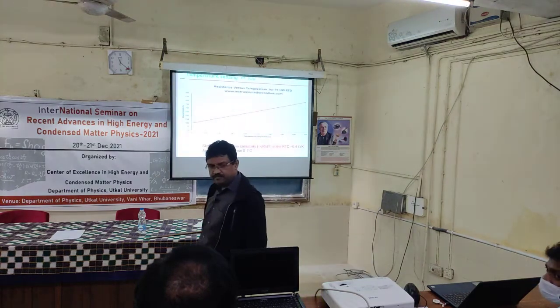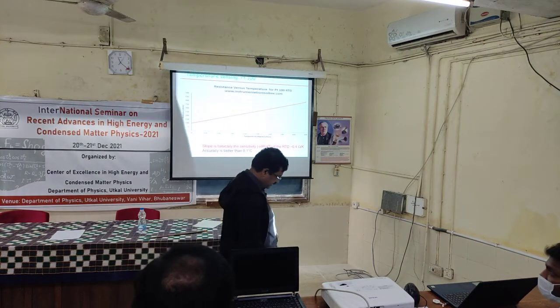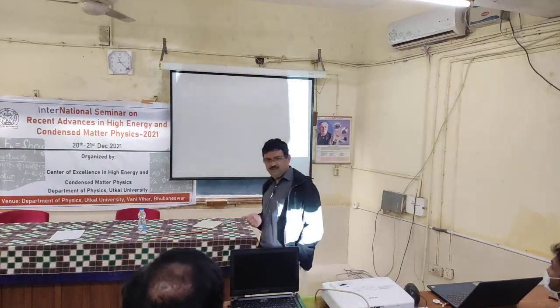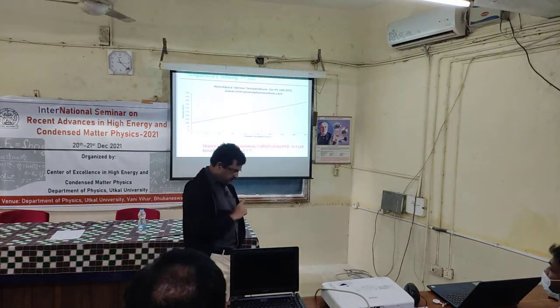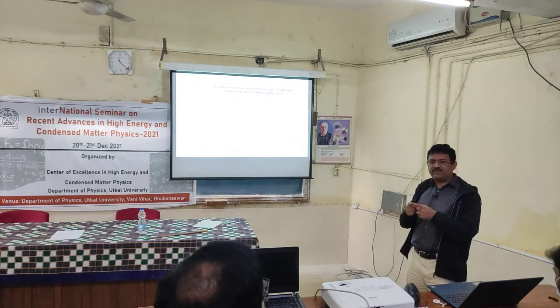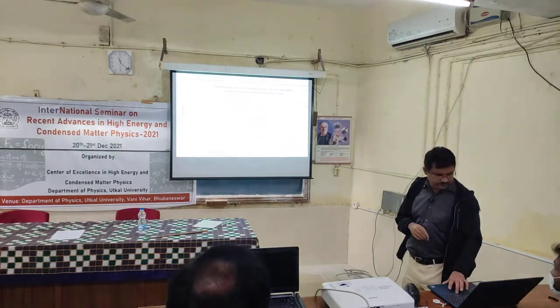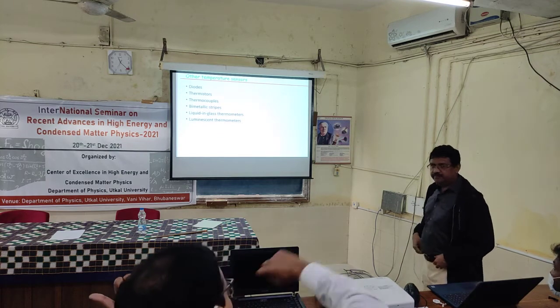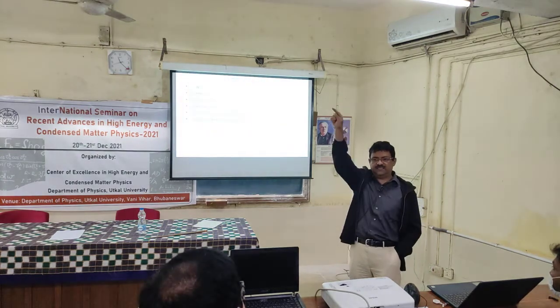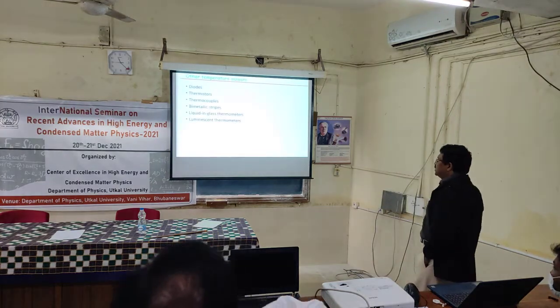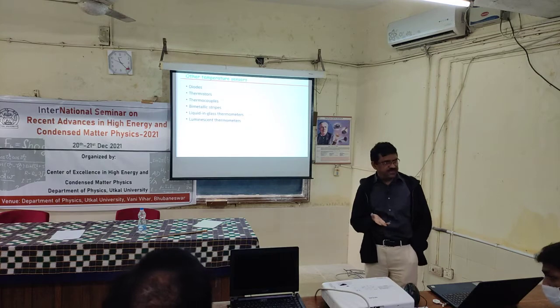Suppose we want to measure the temperature of a transistor or a superconducting material. In that case, silicon is generally used. But if it is a high-Tc superconductor, this platinum 100 can be used, up to minus 260 degrees, and below that of course the sensitivity goes down. It is still linear up to minus 260 degrees. Beyond that, if you look at the RT curve, it goes like this. So diodes and thermistors are again resistance based.